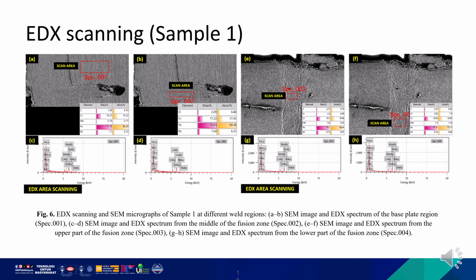But as we do the welding, in the fusion zone in sample 1 we observe a slight chromium nickel depletion, chromium 17% and nickel 6.4% with Fe increasing to 67.2%, suggesting minor elemental redistribution during welding. While oxygen appears in the fusion zone, its level remains significantly lower than in the second sample that we will look at in the next slide.